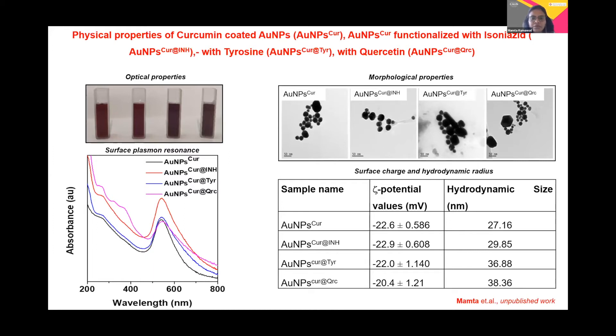In the three subsequent cuvettes, you can see a slight difference in color. This color change is due to the surface modification of these molecules with INH, tyrosine, and quercetin. The SPR spectrum below shows a sharp increase in the peak value between 500 to 600 nm, confirming the formation of these nanoparticles.